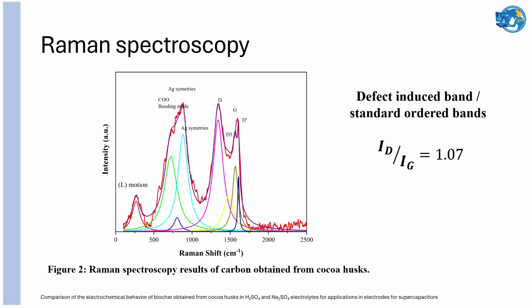The results of Raman spectroscopy have revealed the presence of D and G bands around 1350 to 1400 cm⁻¹ and 1589 to 1700 respectively. These bands are characteristic of carbonaceous materials, and in this case the intensity of the D band, which is characteristic of disordered carbon, is greater than the G band, which is characteristic of graphitic domains, indicating a predominance of amorphous carbon due to the ID/IG ratio. In this case it is 1.07.